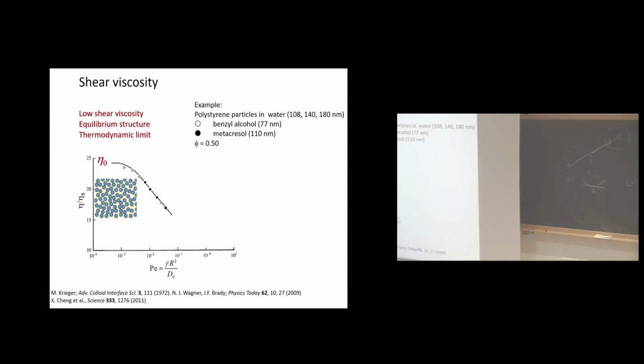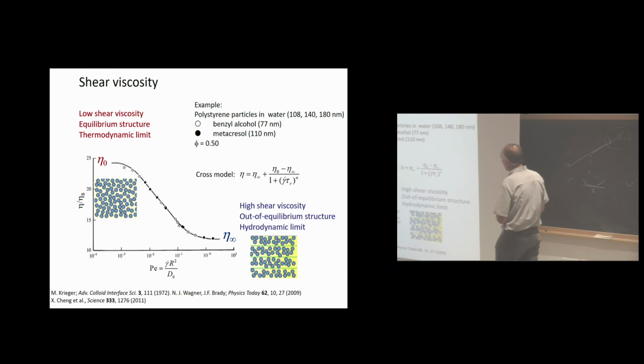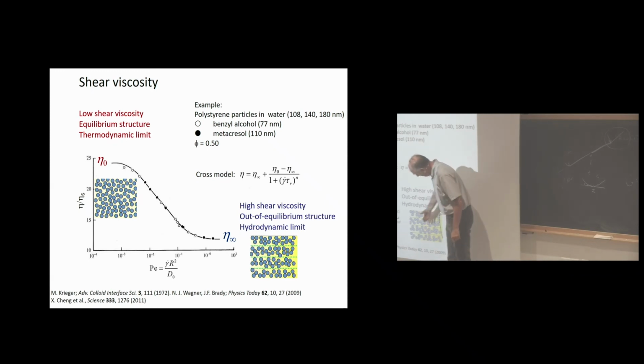So then I have a low Peclet number plateau, which is basically what I will call my equilibrium structure. This is the thermodynamic limit and gives me the zero shear viscosity. But then if I keep on increasing the shear rate, interestingly, I can reach a high rate limit, and this is what we call the hydrodynamic limit. And the cartoon here shows what we expect is happening. So the particles are basically organized in flow, and depending, of course, on the volume fraction, there are different levels of organization, but there are basically stripes of particles in flow, and there are plenty of simulations, but also real confocal experiments that confirm this. Point is that this is equilibrium, thermodynamic limit, this is out of equilibrium, hydrodynamic limit.